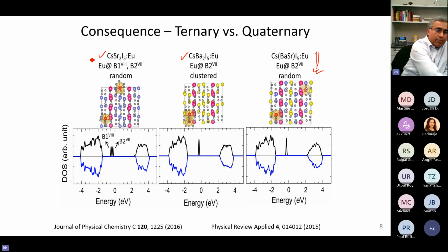You may ask, what is the problem here? Why not go with cesium strontium iodide? There is a little bit of a problem because here you see europium will occupy the 8 coordinated site, also the 7 coordinated site. It does not have any preference. If it occupies both of those sites, you have europium F state there and europium F state there, and the location of those two different europium states are energetically slightly different from each other. When you have two different europium F states, energetically slightly different inside the band gap of the host crystal, then you may also run into some problem with the emission properties because there will be different wavelengths of emission for those two types of europium. So that could be a problem.